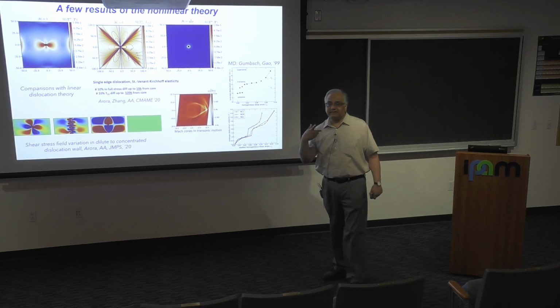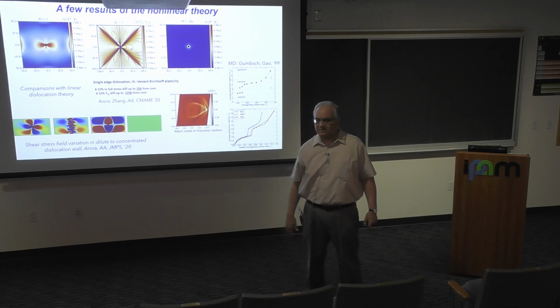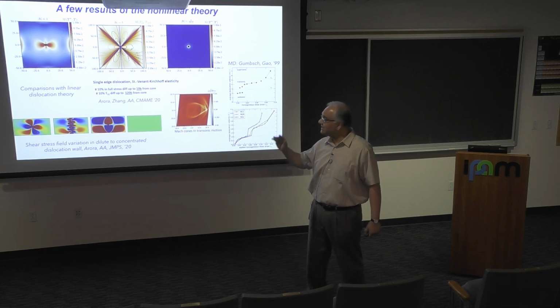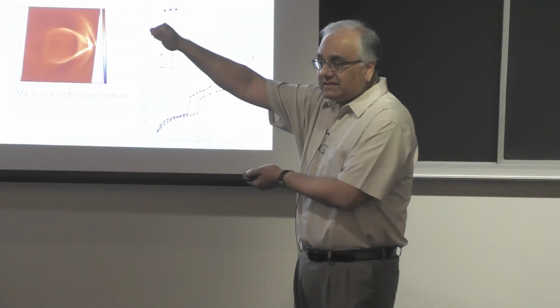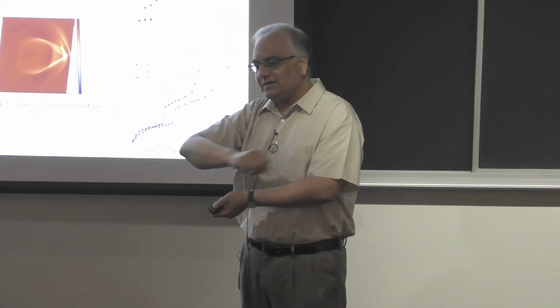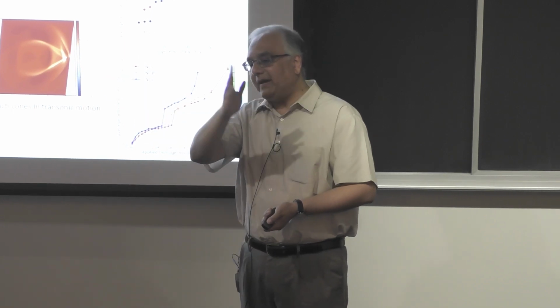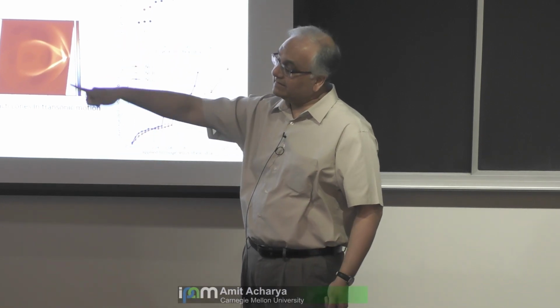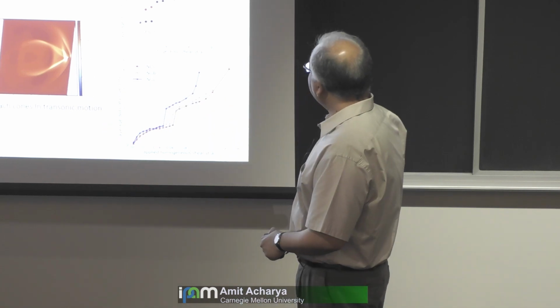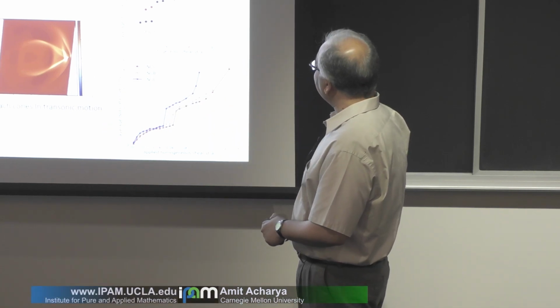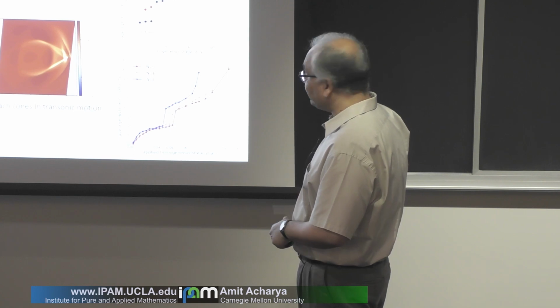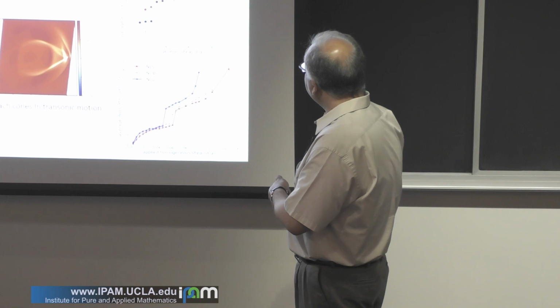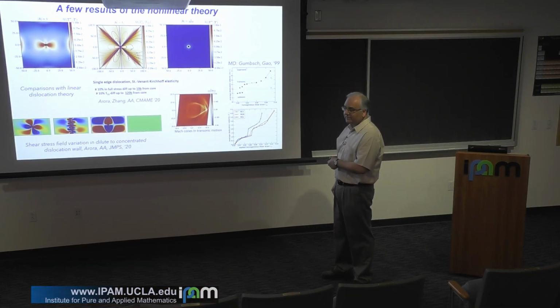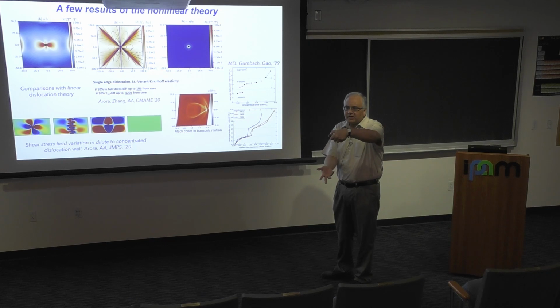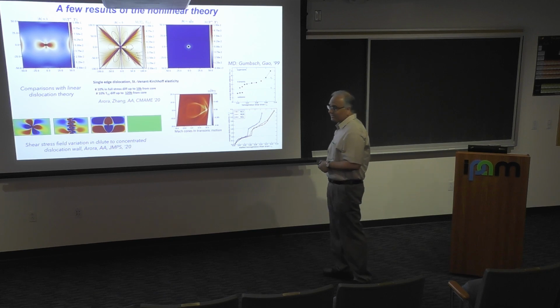Gumbsch and Gao did, because the linear elastic theory dynamics, it breaks down very badly when you approach sonic speeds. So they did this calculation of this pre-stressed sheet with a notch. They launched a dislocation by banging one side, and then because of the pre-stressing, they saw how fast this thing goes. And their MD results, so as you go subsonic, then you have a transonic range, and then depending upon the amount of pre-stress straining that you're doing, you can go above the dilatational wave speed too, because there's an energy reservoir available. If you didn't pre-stress, this is very hard to do. It's probably not going to happen.